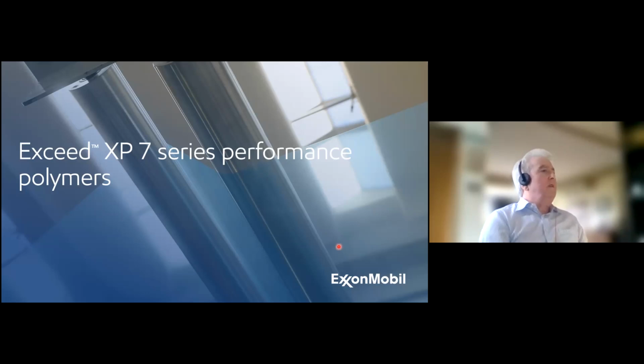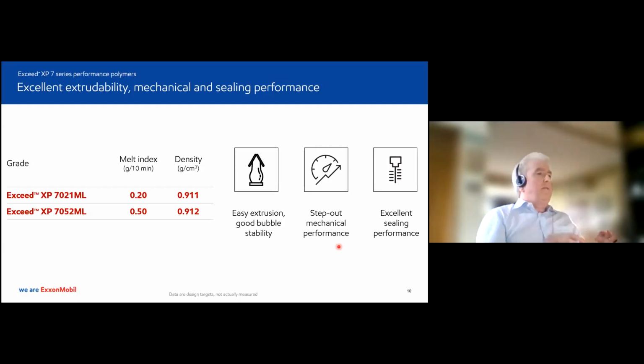Now I'm going to get into the XP7 series, and you can see from the melt index and density here that they're very low in melt index, which already tells you that the melt strength, the bubble stability, and the extrudability is there. But the really interesting thing here is that we've now got the density down to 911, 912, which really now opens up a few more boxes for us with regards to some applications because of the extra mechanical attributes you get by dropping that density, as well as the fact that you're now improving your sealing performance as well.